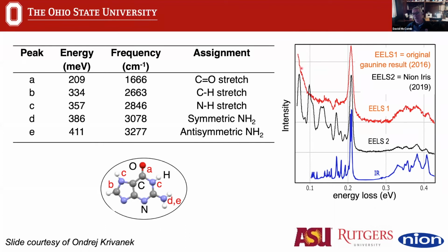And they were able to then collect, back in 2016, this red spectrum showing our EEL spectrum. And now you're also just looking at the vibrational losses. So here in blue is the IR spectrum from guanine. And you can see from the 2016 data that, in fact, we could see a good correlation between the EELS and the IR spectrum. But in black is shown the more recent data that Ondrej Krivanek was able to provide, acquired on a Nion with a new IRIS spectrometer. And I believe this data was done with probably 8 millielectron volts, or maybe slightly better. And you can now see we really are starting to resolve all of this vibrational structure under our EEL spectrum. So this is allowing us to do the equivalent of IR spectroscopy, looking at vibrational losses in organic systems in the electron microscope.